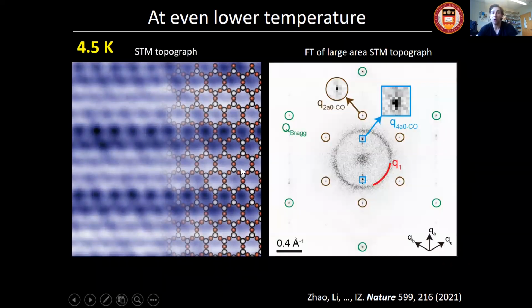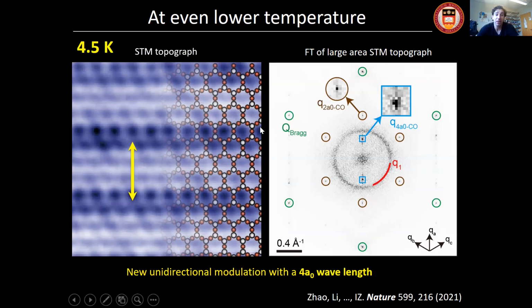And if you do a Fourier transform, the Fourier transform will give you the same peaks as before: the atomic Bragg peaks and the 2x2 charge density wave, but also this peak that in the Fourier transform is easy to miss if you don't know what you're looking for, but it's very prominent in real space as well. And if you zoom in, it's a very clear wave vector of about 4a0 wavelength. So what we uncovered is a new unidirectional modulation with this 4a0 wavelength in these AV3Sb5 systems that was not apparent to bulk probes such as XRD and so on.